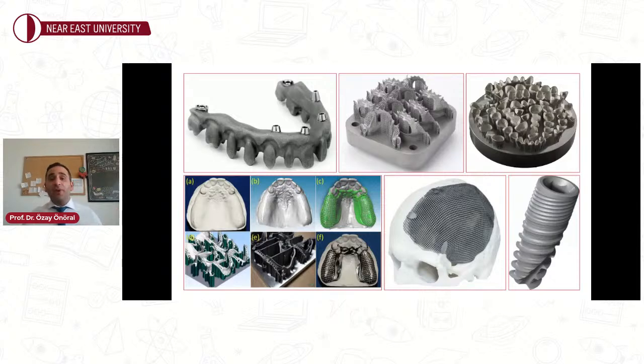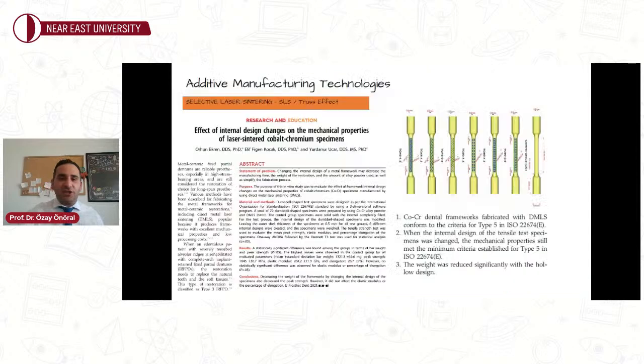The temperature applied by the laser throughout the process should be kept well below the melting point of the metallic powder, and the heat should be sufficient to sinter the particles of the material. The material is not completely melted in this technology. I'm repeating again and again: only sintered, guys, which saves a lot of time during the fabrication.